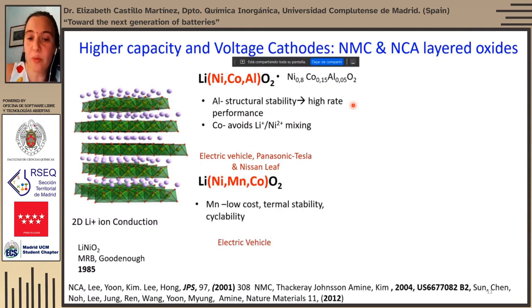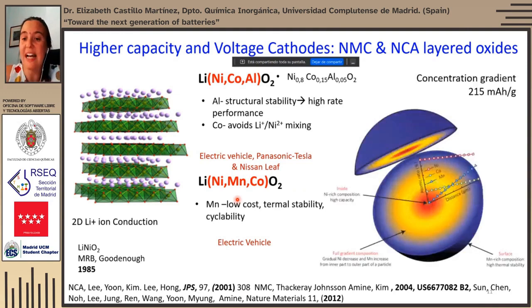The other composition that has conquered the market as well is the NMC, or nickel, manganese, and cobalt, wherein manganese replaces aluminum, which is also another low-cost and thermally stable material. And actually, for this composition, the technology that has been developed and that is mostly used is based on a gradient of composition of spherical secondary particles. So the material is synthesized having a gradient of composition: a pure nickel phase, I mean doped with cobalt to avoid the anti-site disorder, is formed at the core of the particles, but there is a continuous gradient in composition as you go towards the outer surface, and the composition becomes manganese-rich to avoid reactivity with the electrolyte. And this gives a material with a capacity of about 215 milliamp hours per gram, which is quite high compared to the 140 of the lithium cobalt oxide.